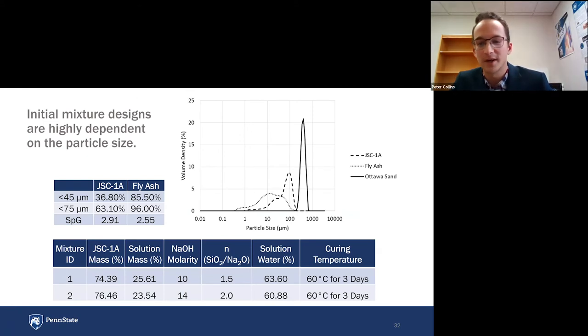So for some preliminary results that we've obtained the last few weeks, I've found that these initial mixture designs are highly dependent on the particle size distribution. Like I said, we're going to compare some of these to a fly ash, and the fly ash is going to be supplemented with an Ottawa sand, which is just kind of the inert filler within the system. Right now, though, I'm trying to use the JSC-1A as is. I just kind of put myself in a scenario that if you're on the lunar surface, what's the simplest way to make this possible without having to sieve and meet specific gradation? So I'm trying it as is right now. And you'll see that